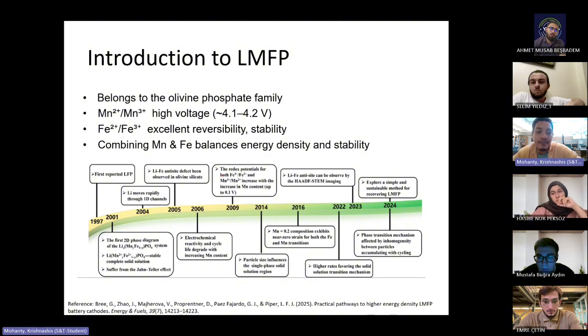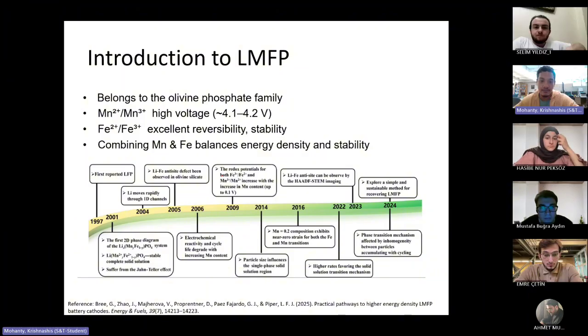Generally speaking, the LFP batteries would have around 130 watt hour per kg, and LMFP, according to lab results, would be able to generate around 160, 165 watt hour per kg in terms of theoretical capacity. And why manganese? The manganese redox potential is slightly higher, not that high, there's not much difference between iron and manganese. So that's the first reason why we pick manganese, as opposed to any other element which has a very, very different redox potential compared to iron.